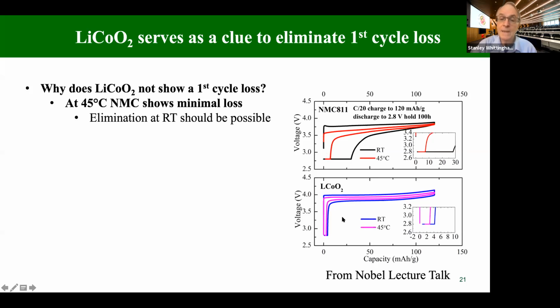Cobalt oxide, in contrast, you see the blue is room temperature, this purple one is 45, and there's essentially no difference. So kinetics is not an issue here, which told us if this little bit of temperature change can make all this difference, then we ought to be able to modify the structure or the electronic behavior to eliminate this difference and make these mixed metal oxides behave more like the layered oxides.